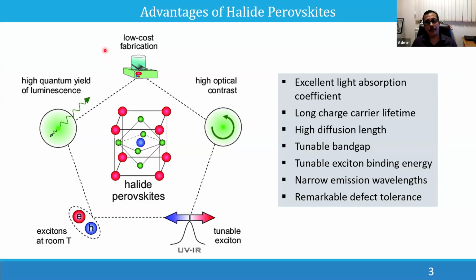You don't require high temperature for working this material in optoelectronic devices. For example, some of the ceramic materials have to be heated to 500 or 600 degrees Celsius to use them as a sensor device. But in this case, this material can be used at room temperature. You don't need any high temperature for using this material for device applications.